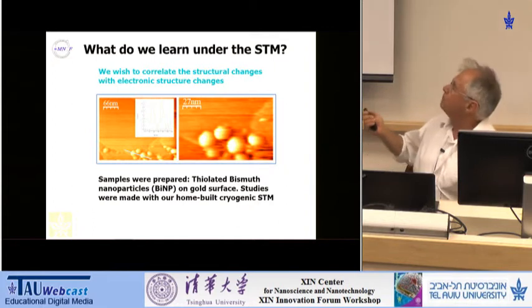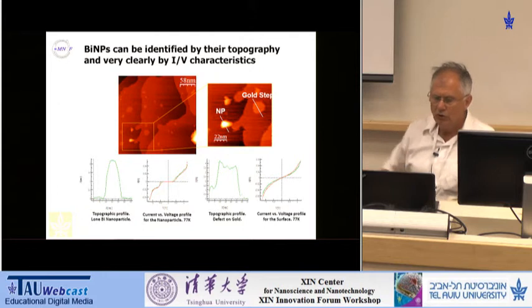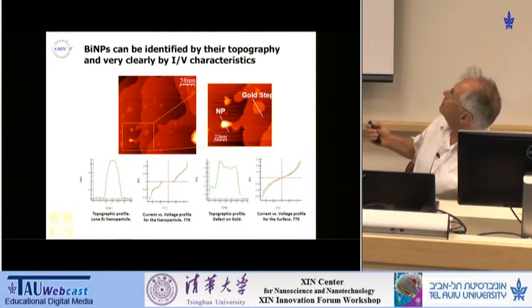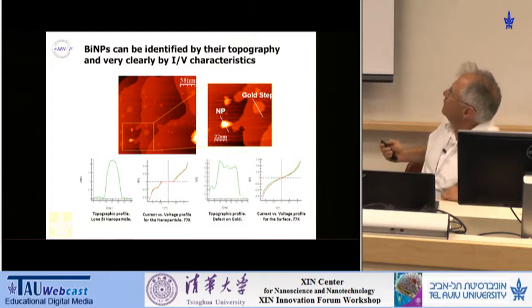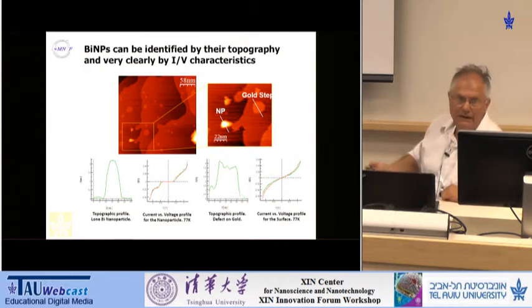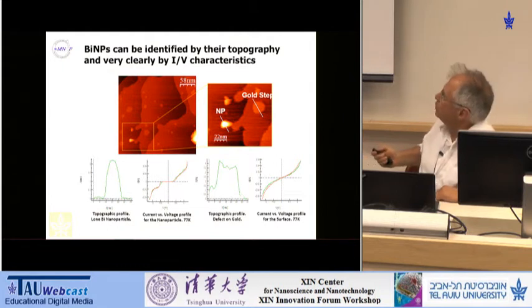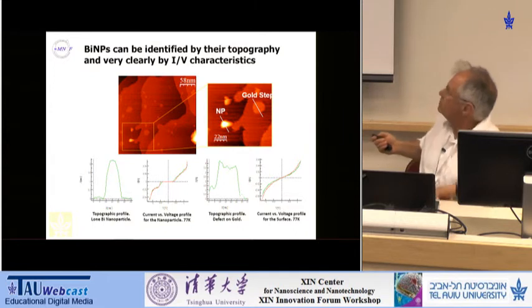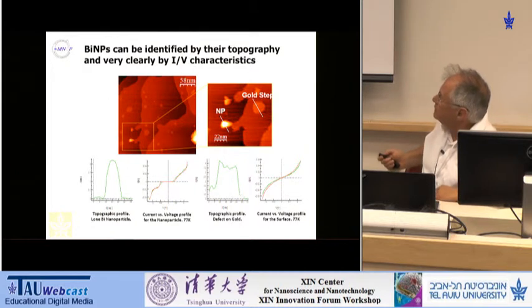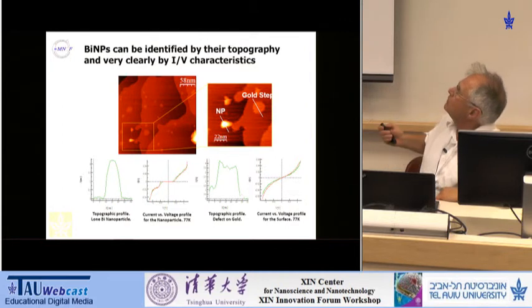So what you see here is those particles, the topographic image. But actually, what you can do is tell exactly whether such a particle is just a step in a gold surface or a nanoparticle. Because if you form a graph of the current through this particle versus the voltage, this is a typical behavior of a metal, a continuous change in the current, exactly like a resistor would do. And what you see in a semiconductor nanoparticle is that there is some region of small voltages where there is no change in the current, although the voltage changes. And this is the fingerprint that this particle is a semiconductor. So you want to know what is this and what is this. This is gold or a metal, and this is a semiconductor.